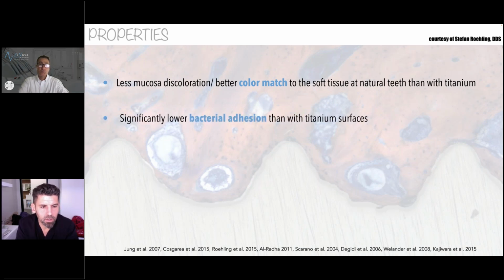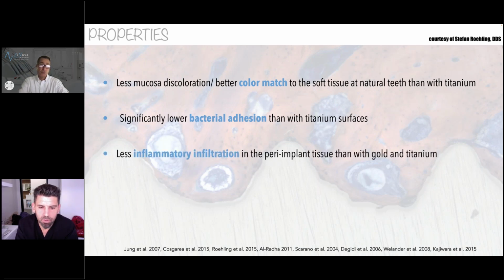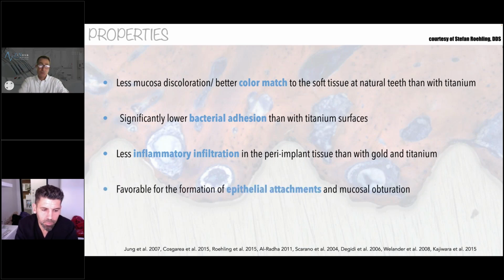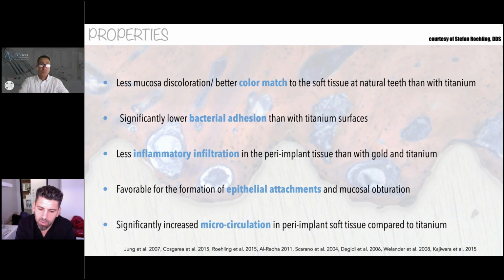We already reviewed the significantly lower bacterial adhesion compared with titanium surfaces. There's also less inflammatory infiltration in the peri-implant tissue compared with titanium and even gold. It is favorable for the formation of epithelial attachments and mucosal obturation. So as I was mentioning, replication of that soft tissue seal that we see in natural teeth, we see that as well with zirconia implants. And there's a significantly increased microcirculation in the peri-implant soft tissue compared to titanium. So overall, a very healthy soft tissue around these implants, and this is one of the more attractive things, at least for me, when using zirconia implants.